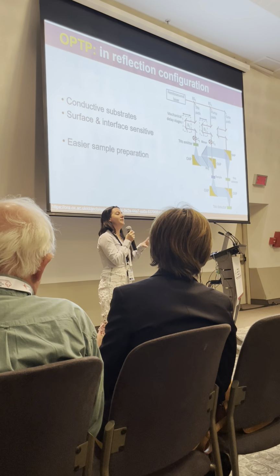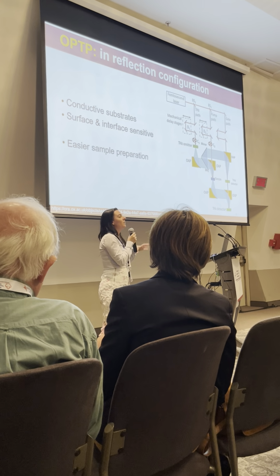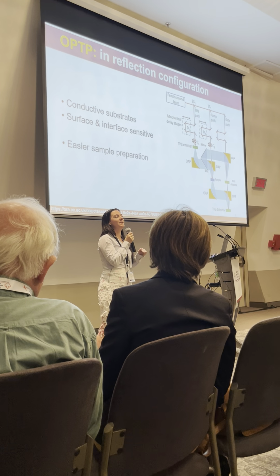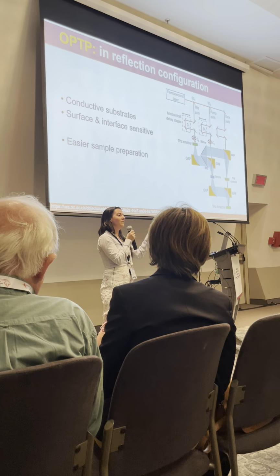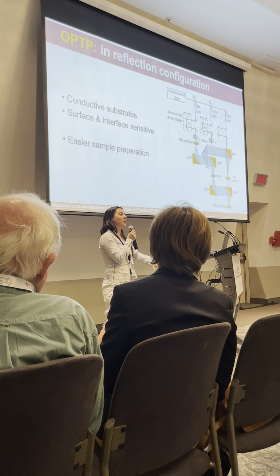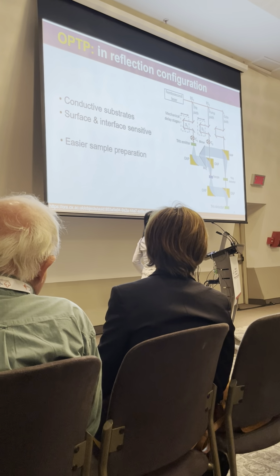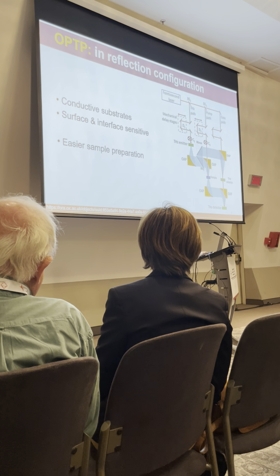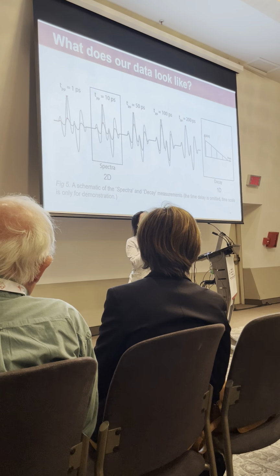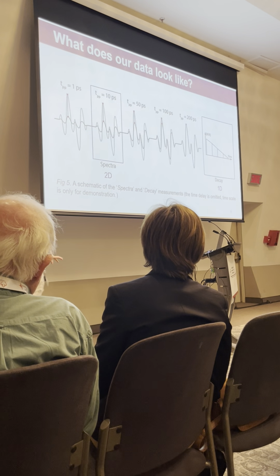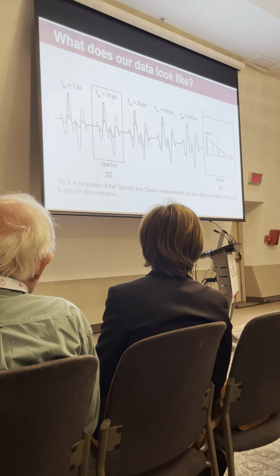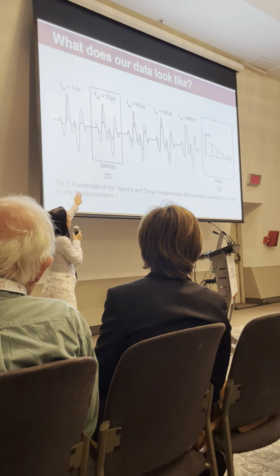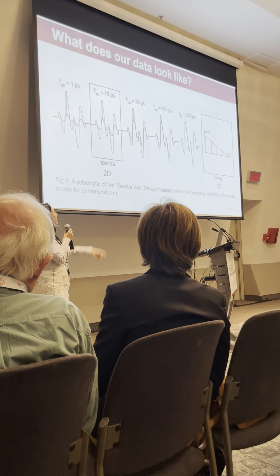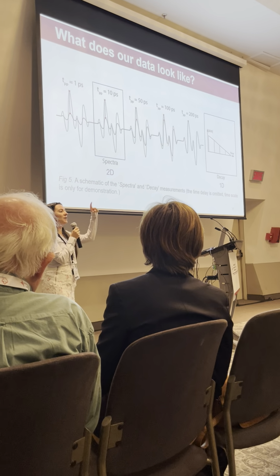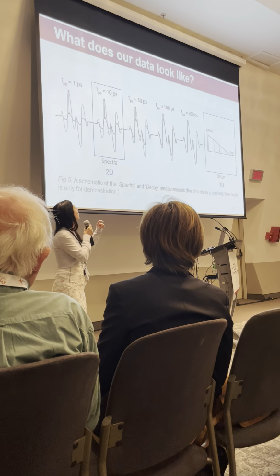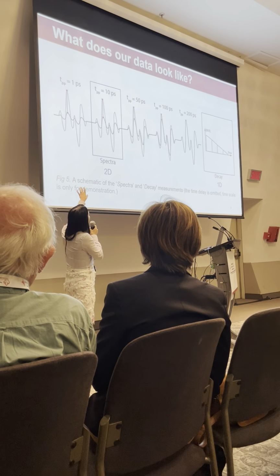We're going to be more surface sensitive in this case, but it is a little bit easier for making those sample preparations. We've got our thin film directly on the substrate that it's grown, so we haven't changed anything to do with the growth of that thin film. So that's kind of one of the motivations for going forward to reflection mode. So we're measuring the reflected terahertz waveform, which you can see in grey here, and then we're photo-exciting our sample, and we're also looking at that change in the terahertz reflected beam. And that's in the darker line here.